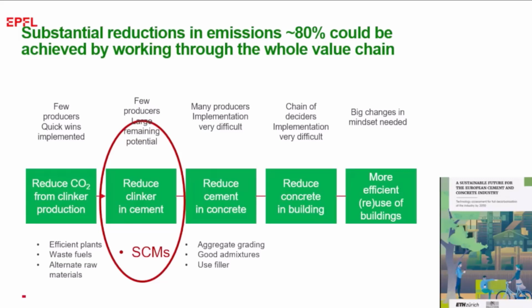But we then have to take it further by making sure that we produce concrete efficiently. And that's usually as simple as using good aggregate gradings, using good admixtures. These are things that have been around for a long time, but they're often forgotten. And we see concretes out there that have 2 or 3 times the amount of cement they need to have. 2 or 3 times the amount of cement means 2 or 3 times the amount of CO2.